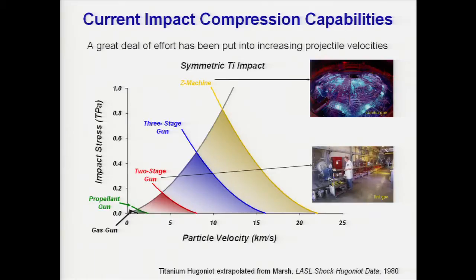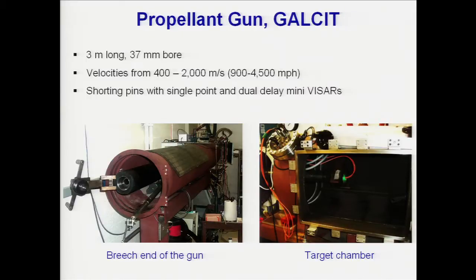In the university atmosphere at Caltech, we operate with gas guns, propellant guns, and there are also two-stage guns available. The range of velocities which we can create in my lab is 1 to 2 kilometers per second. What we are doing in my lab is that we take a powder gun, or propellant gun. This is a Navy gun which was refurbished from the Second World War, and we fitted it with a powder breech. We load this with propellant and ignite it using a cartridge, and this generates high pressure propelling a projectile which impacts a target in the chamber, which is highly instrumented.